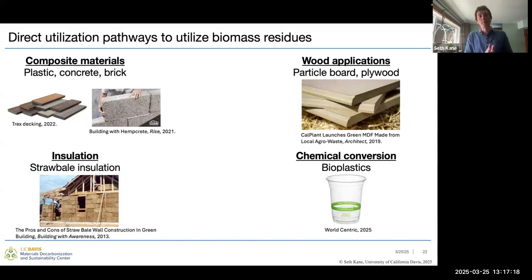In addition to those thermal conversion pathways, we can use some of these biomass residues directly. So that might be, for example, in a composite material. One that a lot of people are familiar with might be Trex decking, which utilizes sawdust in a polymer composite. But there's also things like hempcrete. You can potentially use some of these biomass residues in place of primary wood in particle board and plywood, and that's been done by a number of startups. Straw bale insulation is an example of using these biomass residues as an insulation material, or you can chemically convert them, be that either to bioplastics or in a biorefinery to separate out, say, the cellulose component of that, and use that in more valuable products.